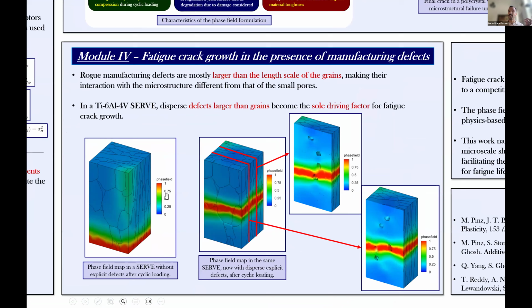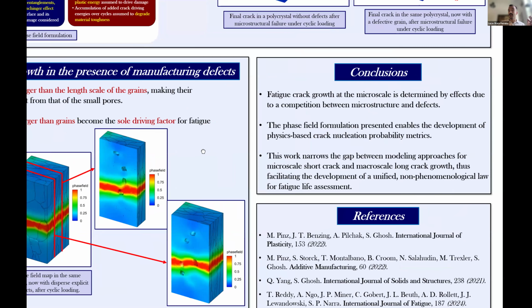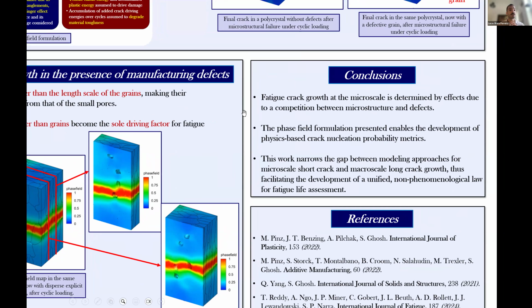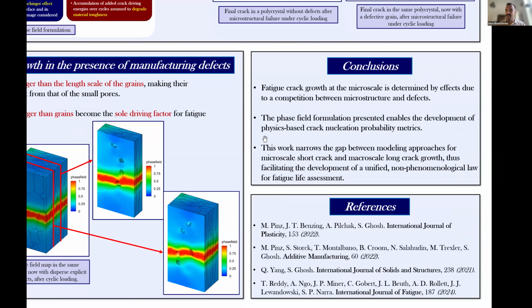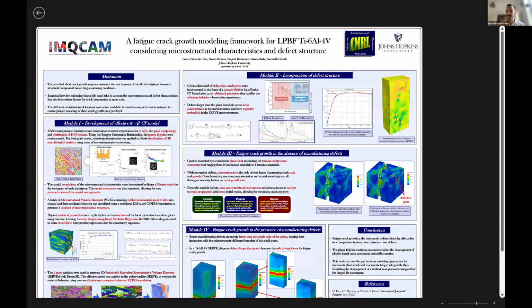But now, once we have actual larger defects, we were able to see that, depending on the size of the defect, the microstructure doesn't have such an effect on the crack path anymore. The crack is going to go through these large defects because it enhances the stress concentration and all of that. So with this work, we were able to capture the competition between microstructure and defect in determining crack path, and this enables us to narrow the gap between using a formulation for fatigue life assessment that takes into account the microstructure, but also is capable of predicting the long crack growth. And with that, I thank you very much for listening to me, and I'll take any questions.